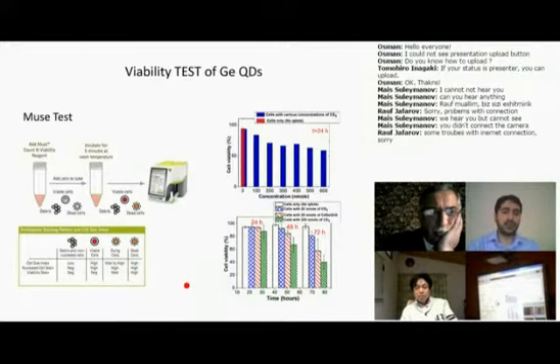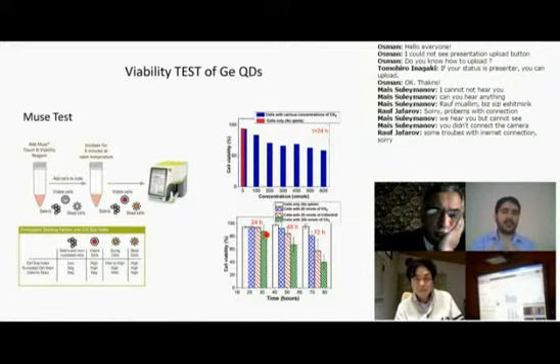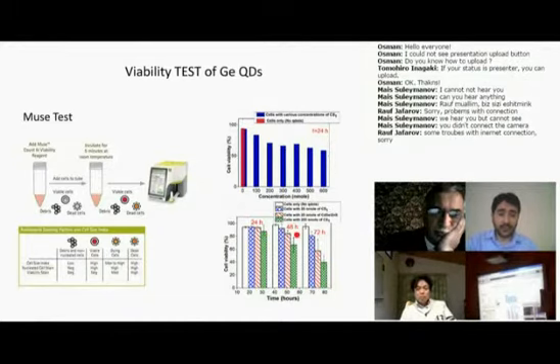In order to understand the toxicity effect, we had a look. We did the Muse test, which basically means that we put our particles in cells. Actually, the intake is done by the cells, and also we had a look at how many cells died after intake. We did a comparison here at 24 hours, and during 3 days we did some measurements.